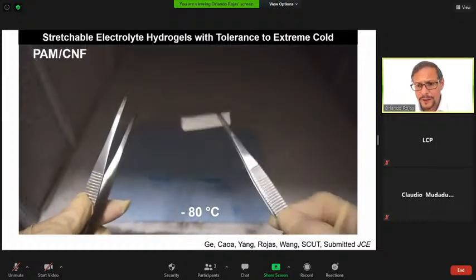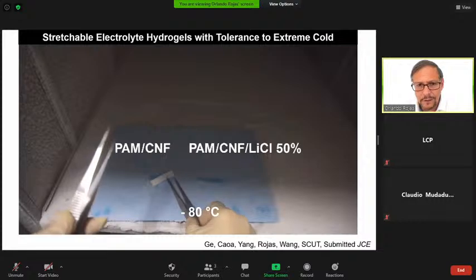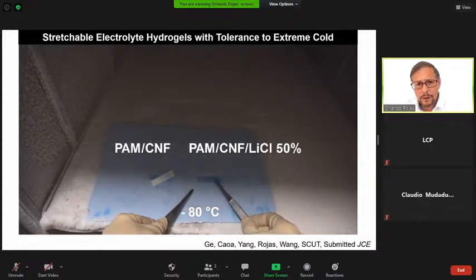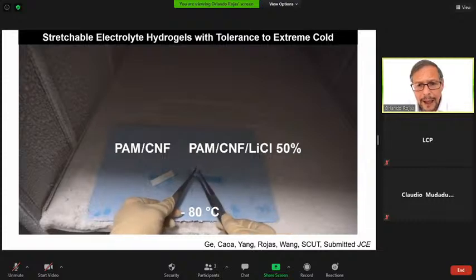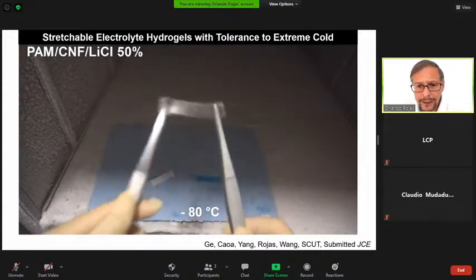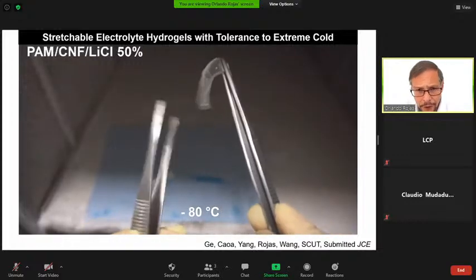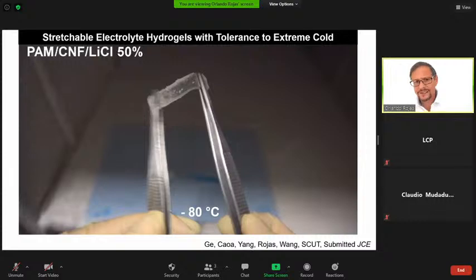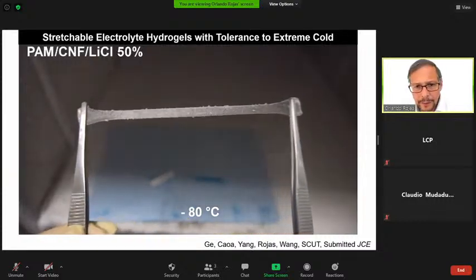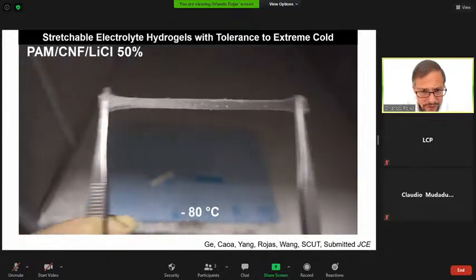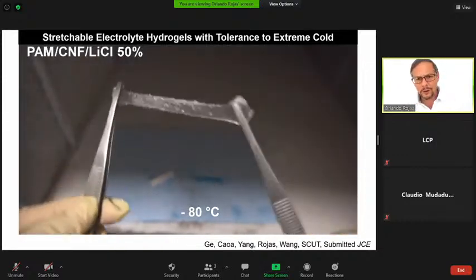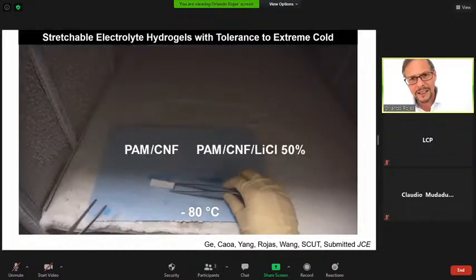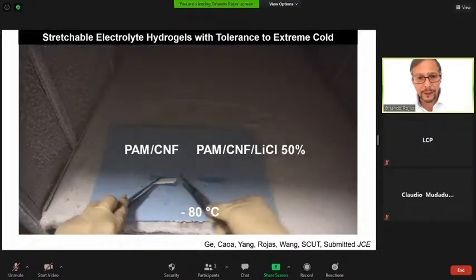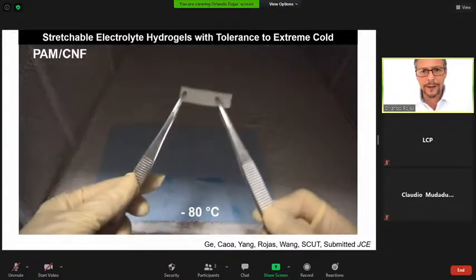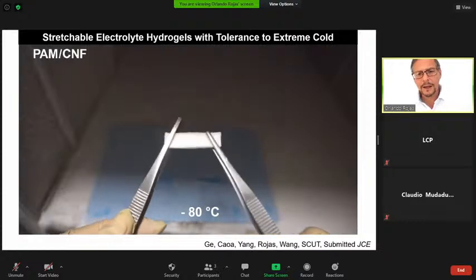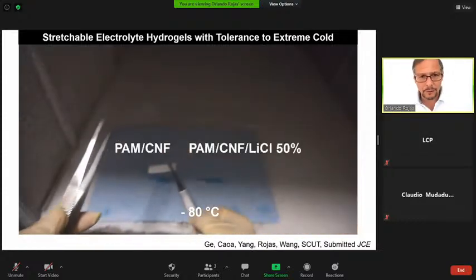I want to also show something that is ongoing, work with the South China University of Technology, where we have combined cellulose nanofibers with polyacrylamide. And then we have added a very well-known electrolyte, lithium chloride, that is a hydrogen bonding disruptor. And this is quite interesting because with this type of hydrogels, even if we go to sub-freezing temperatures, in this case, minus 80 degrees, the hydrogel still remains very extensible and strong. And that's very interesting. If you compare the one on the left in the absence of lithium chloride and the gel on the right that contains the lithium chloride.